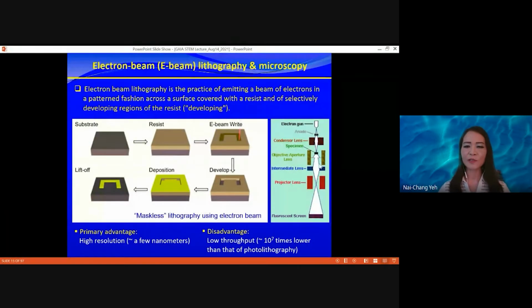For electron beam lithography, this is schematically showing that you have electrons that come out, and you have optics that are electromagnetic fields that behave like lenses in optics and then focus the beam. Then you can project the signals out to some kind of screen or detector. Now, if you want to develop patterns, electron beam has very good resolution. You put some resist on the substrate, then you use the beam to write very fine features on it, and you develop it. You deposit whatever metal you want, and then you remove the polymer and lift off. Then you get the structure that you want. So you can do maskless lithography using electron beam.